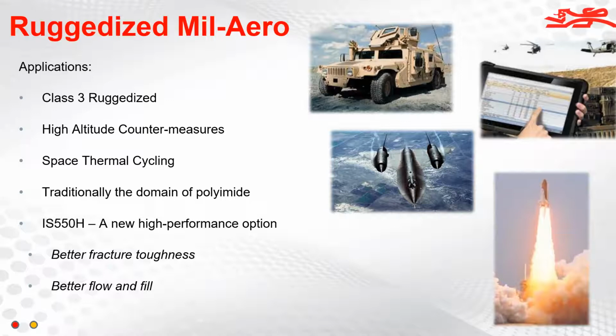It has a much better fracture toughness. You can actually drill through these clearance areas without the fracturing. So it actually is going to enable the designers to get the thermal robustness that they need in a resin system and keep the heavy copper that they really wanted in the first place. Yeah, temperature cycling, at these extremes, can be real hard on the material. And, again, something that doesn't crack or fracture, that's a big benefit. I've seen customers in their design using polyimide for high temperature applications have to add layers because they can't go with a single or fewer thicker copper layers.